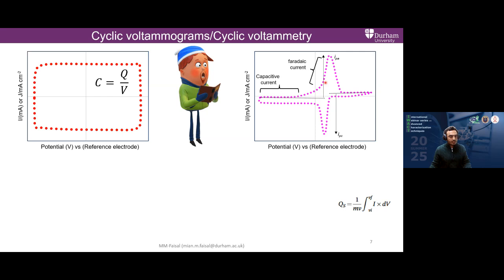So how can you then determine whether your material is behaving reversibly or irreversibly? You can take the ratio of the peak currents of oxidation and reduction. If it is nearly equal to 1, then that means the performance is reversible. Another way of doing it is getting the number of electrons involved in the cyclic voltammogram, and then 59 divided by n millivolts is the exact difference between the oxidation and reduction peaks. If the difference lies around 59 millivolts for a one-electron system, that is reversible. If it is less than or more than that, then there is certainly some problem with your system, and you have to identify that problem before going further with that material.